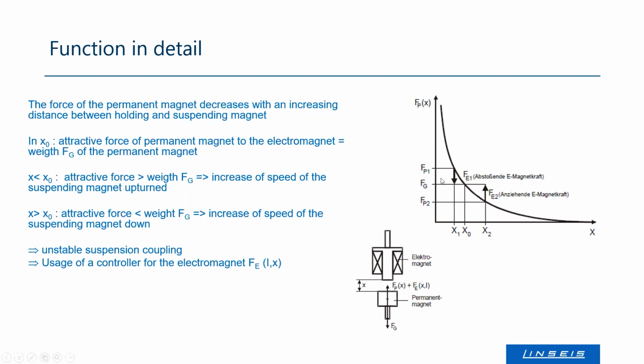So this graphic just explains there's a range where there's a balance between the magnetic forces. So the electric magnet and the floating magnet, they see attraction to each other. And if they are at the right distance, it will be kept at the same distance all the time. If you lower this distance, the attractive force would be increasing. So if you lower the distance, the attraction force increases and the floated magnet would be pulled up and finally touch the chamber hull or the end of the chamber. Therefore, you have to lower the magnetic force of the electric magnet.